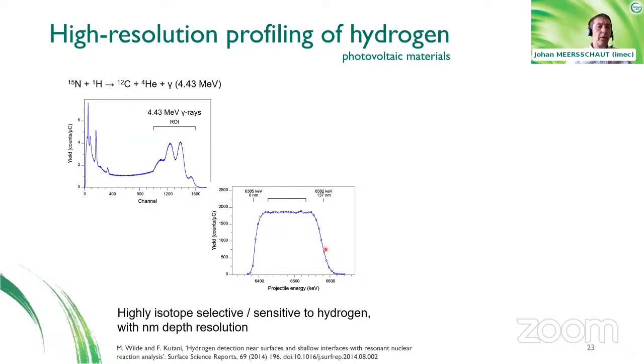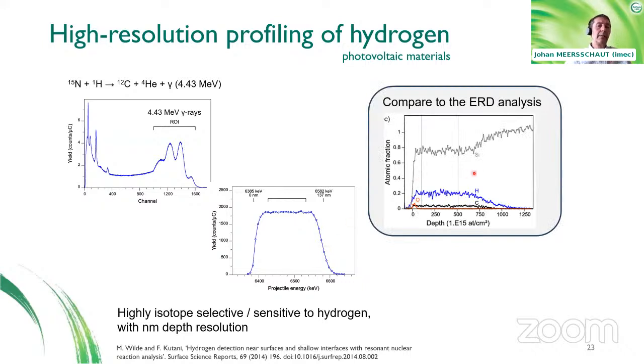And just to compare this with the other technique that I mentioned earlier, this is the depth profile obtained with elastic recoil detection analysis. You see here that the statistical uncertainty is much lower as compared to elastic recoil detection analysis. On the other hand, with nuclear reaction analysis, you only probe one specific isotope at a time, whereas with elastic recoil detection analysis, you probe all the elements together. But it gives you a very isotope selective probe for the depth profile, in this example for hydrogen, with a very good sub-nanometer depth resolution.